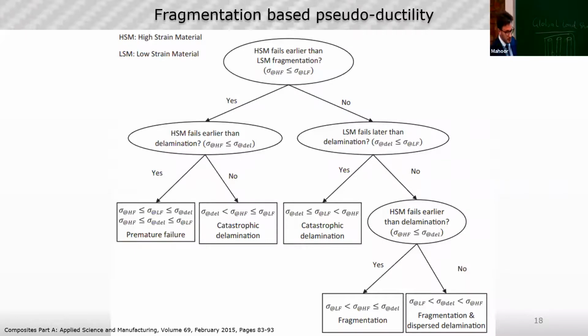The generation of the damage mode map, which by the way is a very useful tool for designing material, for designing hybrid composites, and especially if you want to have pseudo-ductility, is a parametric process where for each scenario we compare the delamination stress with the fragmentation stress. If the fragmentation stress is lower than the delamination, we get fragmentation instead of delamination.